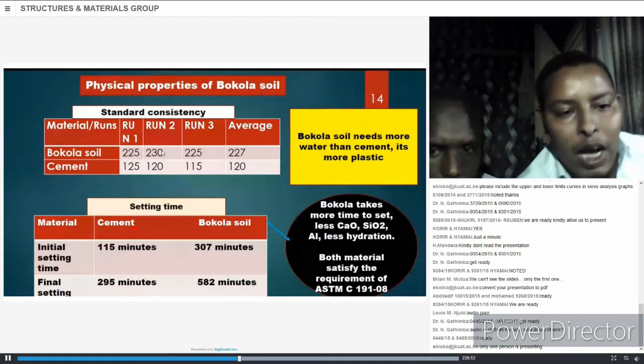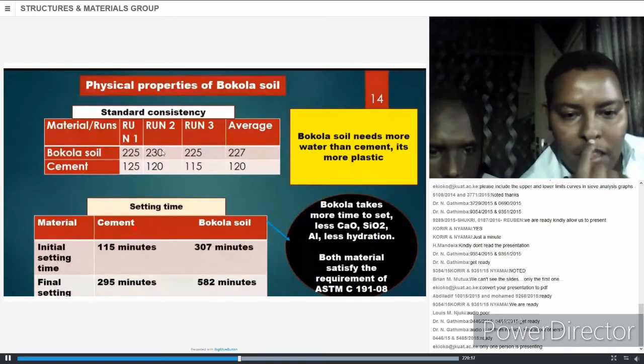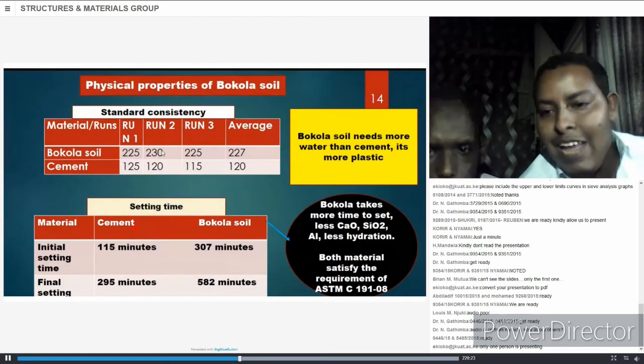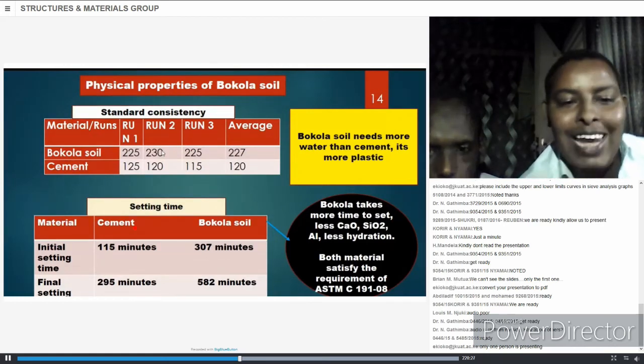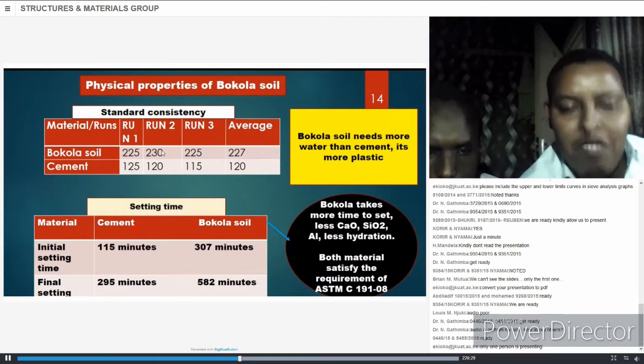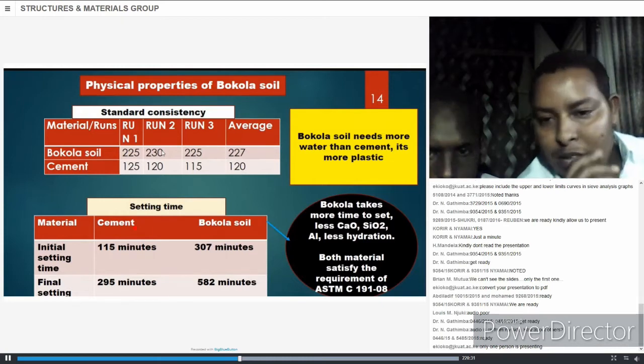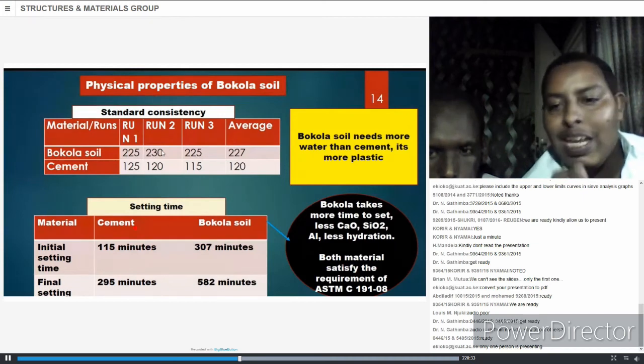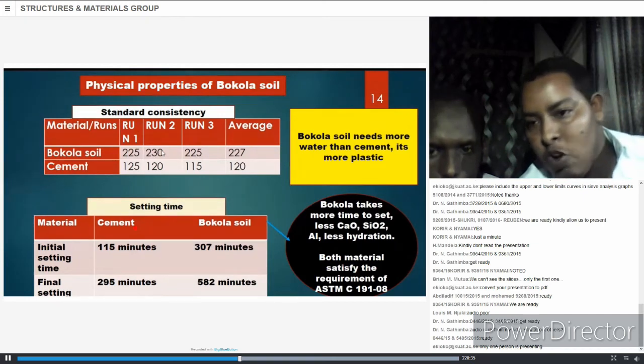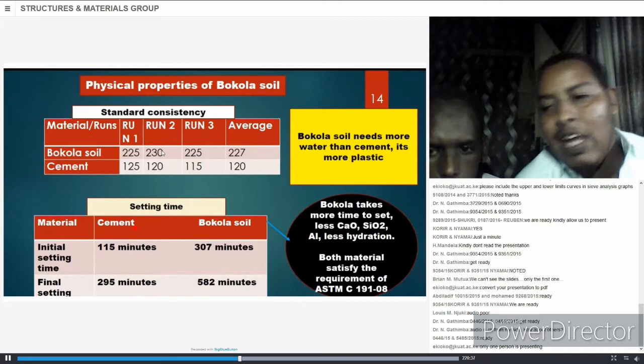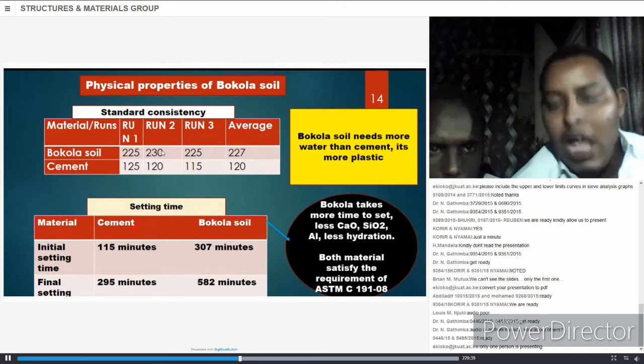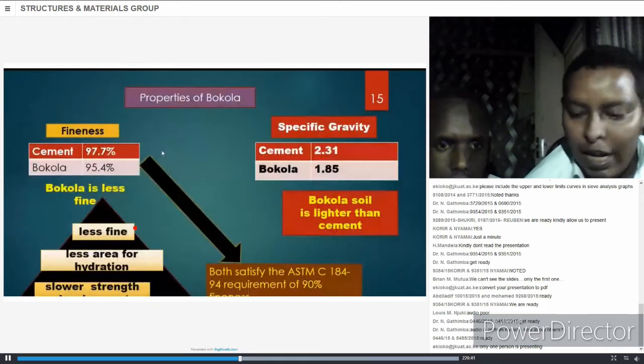Setting time: the initial set for cement is 115 minutes, bokola is 307. Final setting for cement is 295, the other one is 582 minutes. Although both met the ASTM requirement of not less than 45 minutes and not more than 10 hours, we realized bokola needed more time to settle, and this is because of less calcium oxide and less silica. This means less hydration and fewer reactants.